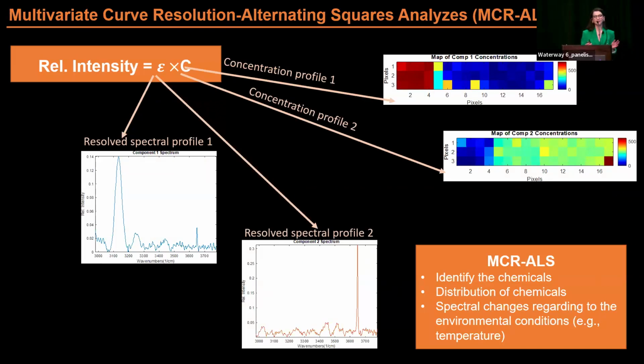And here, what I have done is to use multivariate curve resolution alternating least squares analysis. That's a chemometric method to find out what types of samples you have and the mixture inside, plus how they are distributed between the samples. With this model you can also extract the pure spectral components with the concentration profile. The concentration profile refers to any other experimental parameters, which can be temperature, pressure, pH, or any other variable factor that you use.